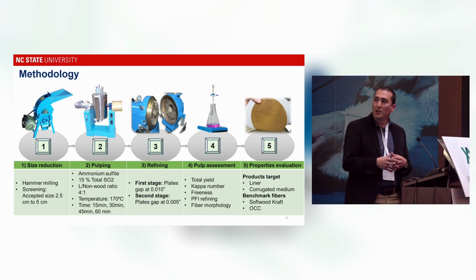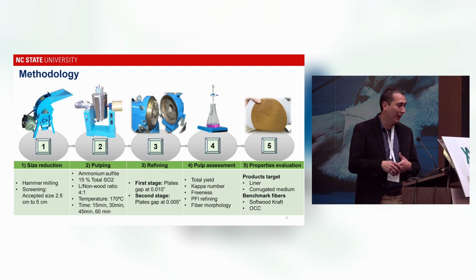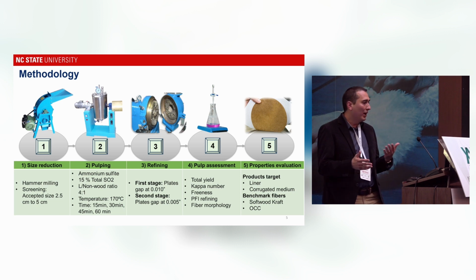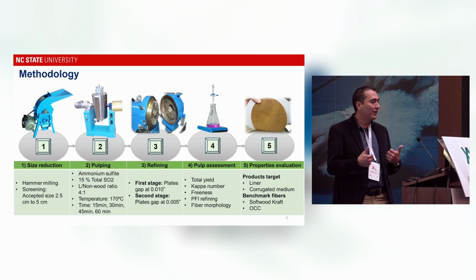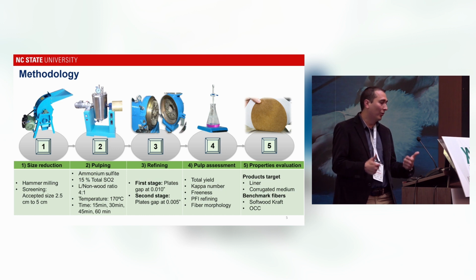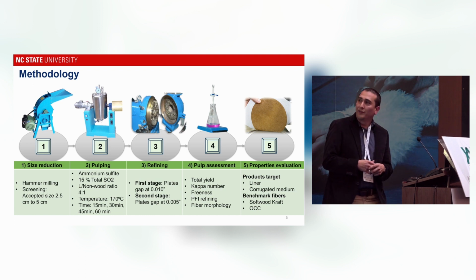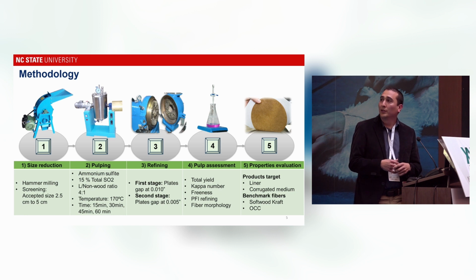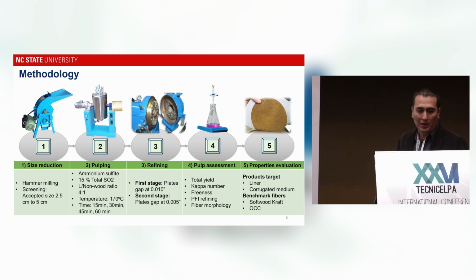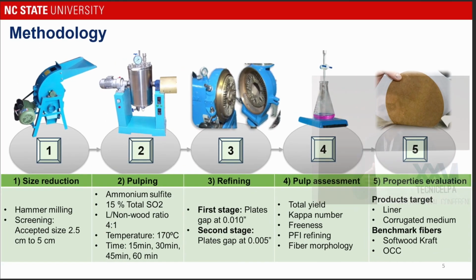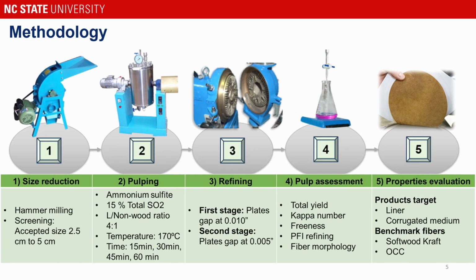So as you can see here, we are changing the cooking time, and we want to see what is the effect of the cooking time on those pulps. So then after pulping, we refine those pulps using 2 stages. And we evaluate the total yield, the kappa number. We also evaluate the refining of those pulps and fiber morphology.